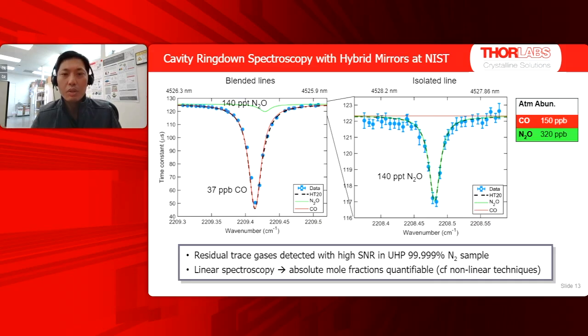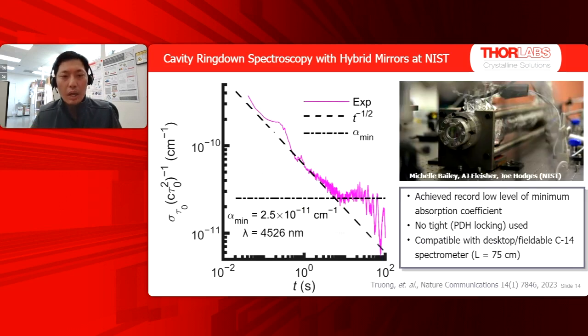And indeed, if they moved the spectrometer to a wavelength where N2O has an isolated line, they were able to confirm that, yes, there was 140 ppt of N2O. And to give you some idea, the natural abundance of N2O is 320 ppb. So that's pretty impressive in my books. Shows you sort of how sensitive this technique can be. And with a little averaging down to a few seconds, we see a minimum absorption coefficient of 2.5 by 10 to minus 11 per centimeter.